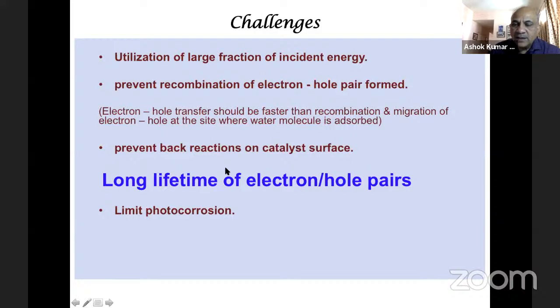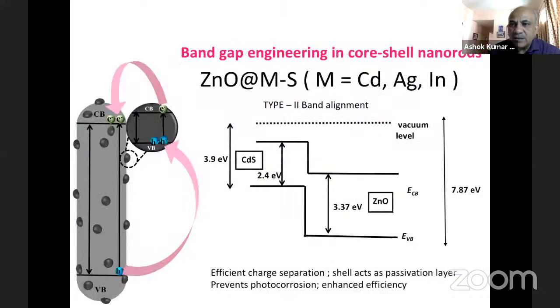We want as many photons to be absorbed as possible, and we want to limit photocorrosion. That means your material should not get degraded in light if it is kept for a long time. So one of the examples that we did was to create a core-shell type of structure of two semiconductors. One is a UV catalyst, zinc oxide, in the core, and the shell is made of cadmium sulfide, silver sulfide, or indium sulfide, one of these. So we made all of them.